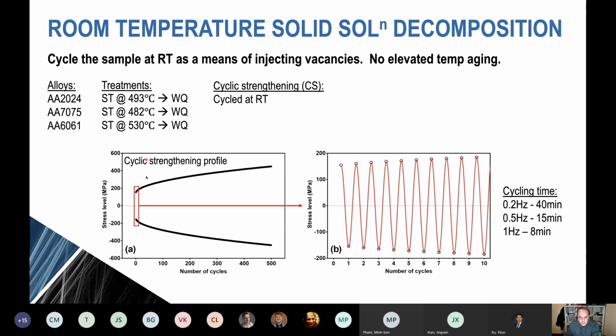And then for each of them, we've designed a particular cyclic profile. And so this profile is designed in a very particular way to control the dislocation motion during cyclic plasticity. We want to drive dislocations back and forth so that they can generate vacancies, but we're not trying to strain harden the material. In fact, we're trying to minimize the amount of dislocation accumulation by traditional forest hardening. We just want to move the dislocations back and forth. And so the way we control this is by controlling the plastic strain amplitude, and we try and keep that down around 5 × 10⁻⁵ or 1 × 10⁻⁴.